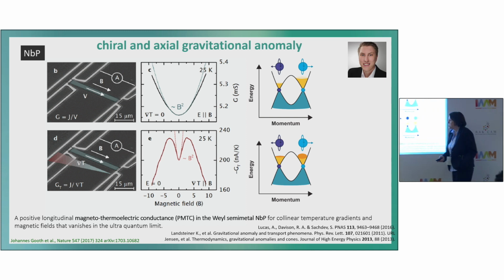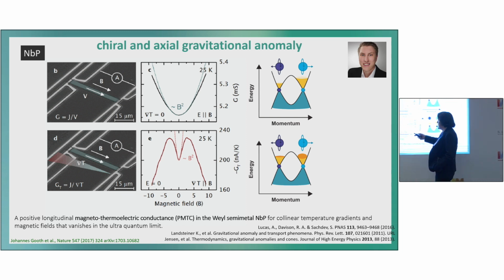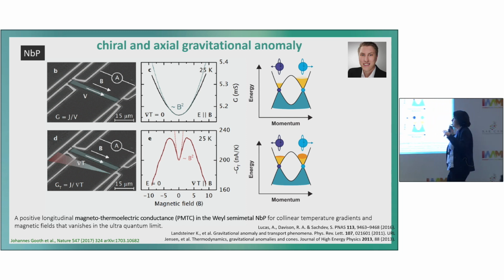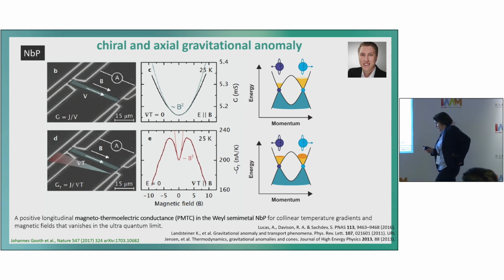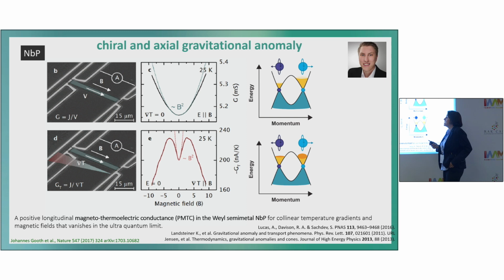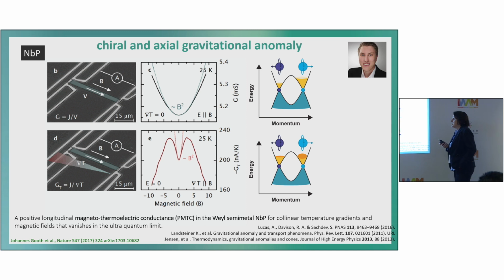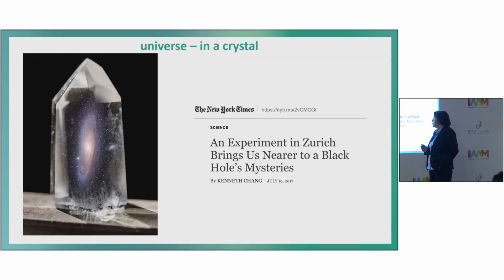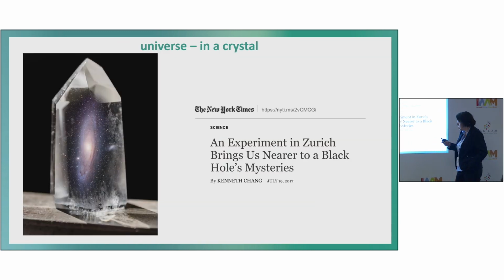For example, in bismuth itself, you can make bismuth a Weyl semimetal by doping with antimony, and the group of Joseph Heremans even shows this effect up to room temperature, this thermal version of the chiral anomaly. So it was already interesting for us that you can see these features in materials, and we thought, can we use this in the future, with these chiral electrons, maybe for chemistry and catalysis. We did some catalysis already on this, but I do not have the time to talk about it since I want to focus on the chiral system.